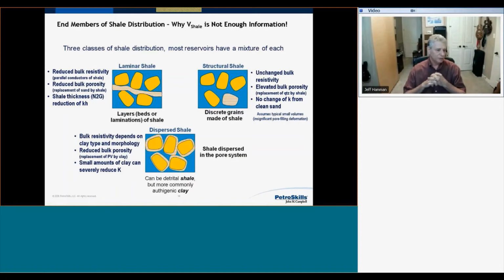And maybe the most important part of this for laminated stuff is that the shale thickness, so a V shale or a net to gross, really reduces the permeability thickness product only by thickness. In this particular case, we have retained the permeability of the sand, and so we can have a quite productive system because of the sand permeability. We just lost the thickness of the system. Okay, so that's a very key part of this whole process.